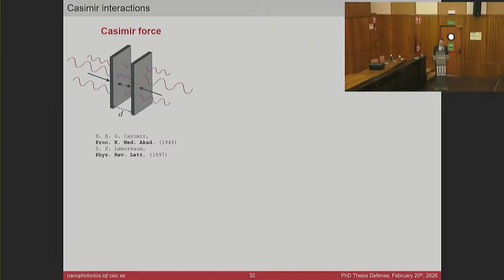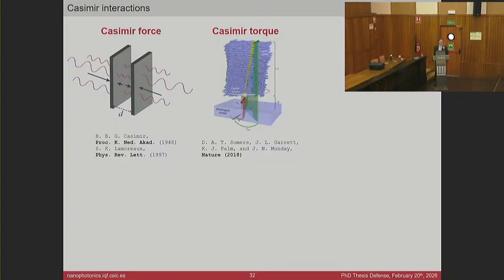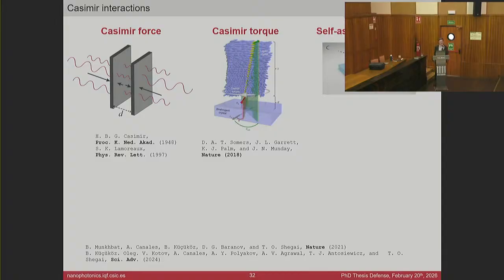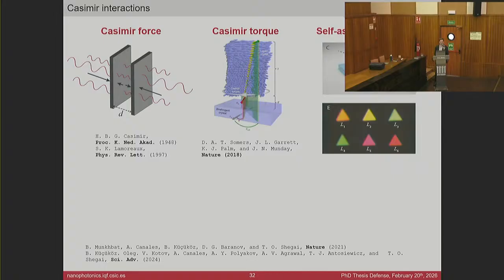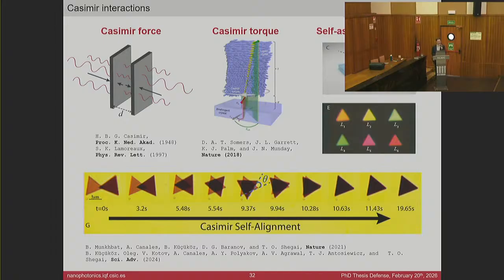Let's see some more examples. There is also an attractive force known as the Casimir force between two conductive plates that is many times explained because of the different density of photonic states outside and inside these two conductive plates. If we break some symmetries of the system, for example, by considering anisotropic objects, we can also obtain a Casimir torque. And while these phenomena are really interesting by themselves, they can also have applications. And recently, they have been utilized to build self-assembled cavities that, depending on the properties of the nanostructures and the surrounding medium, can have different optical resonances that we see here as different colors. And they could even study in real time the Casimir self-alignment of this nanocavity in a time scale of seconds.